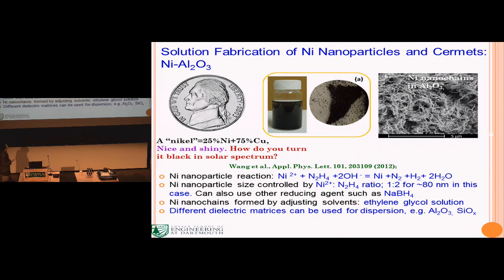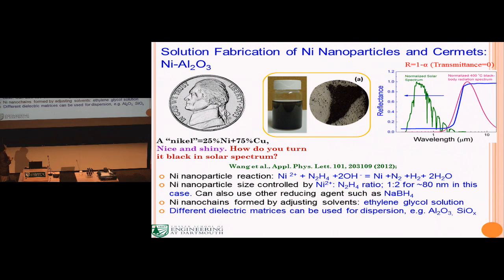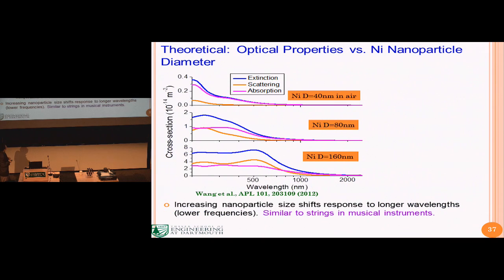In this case, the matrix is aluminum oxide. And you measure the optical properties. Indeed, it has low reflectance in the solar spectrum regime and high reflectance in the IR regime. So how does that work? It's all about the coupling between light and free electron oscillation in nanostructures.